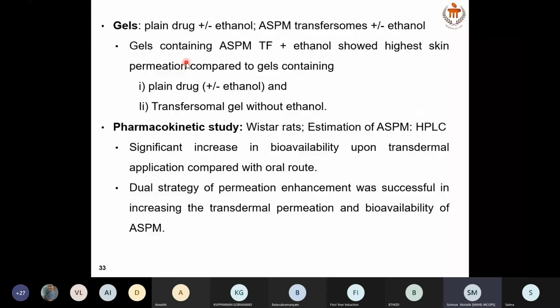Initially we prepared the transfersomes containing ASPM, asenapine maleate, and then we loaded into the gels, that is plain drug plus or minus ethanol, and ASPM transfersomes plus or minus ethanol. The permeation studies showed that the combination of nanoparticles or transfersomes along with ethanol gave better permeation into the skin, across the skin.